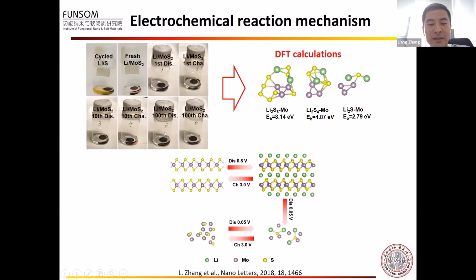This is confirmed by the experiment here. For the second electrode, we didn't see any color change for the electrolyte, because the polysulfide in the electrolyte has a golden yellow color. Here we can see the electrolyte is still transparent. This indicates a strong interaction between the moly and the lithium polysulfide. The bottom picture shows the conclusion of all experiments. The intercalation reaction is reversible with the phase transition from 2H to 1T. The conversion reaction is not reversible. The final discharge product is lithium sulfide and moly, and during the following charge process, the lithium sulfide is converted to sulfur, and the moly sulfide structure is not recovered.